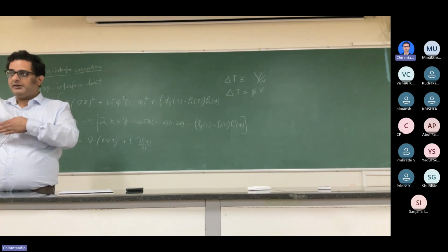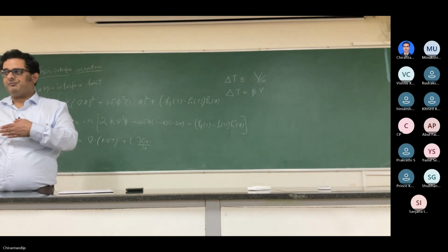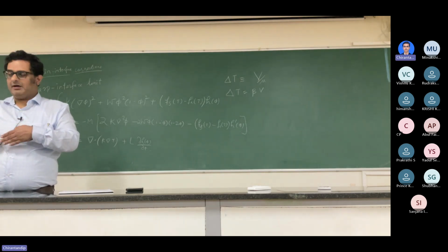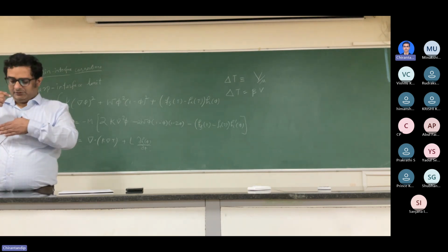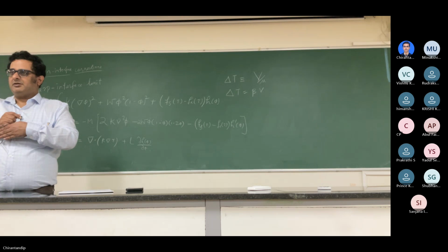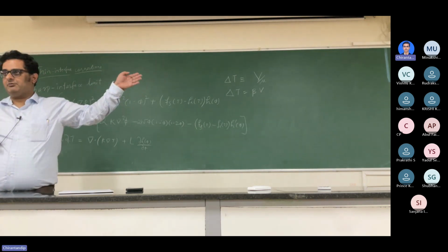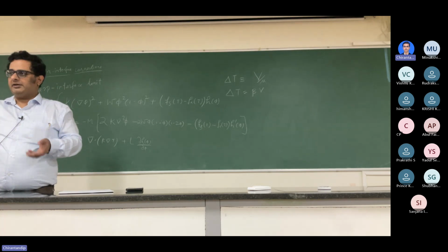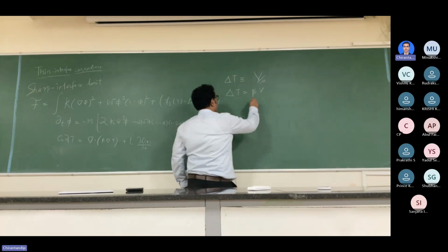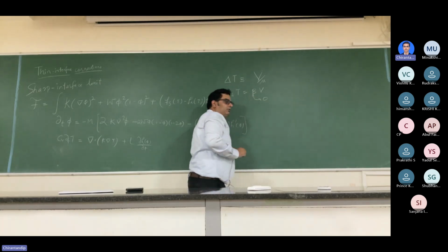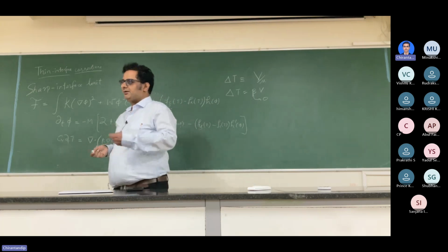That means you need an undercooling at the interface when you are driving the interface with a given velocity. On the other hand, if you have an atomistically rough interface, the kinetic coefficient, the beta that you have in an interface kinetic coefficient, is rather small, and the undercooling is rather small. So what you have is a situation that beta tends to 0 for most situations that are relevant to castings under realistic conditions.